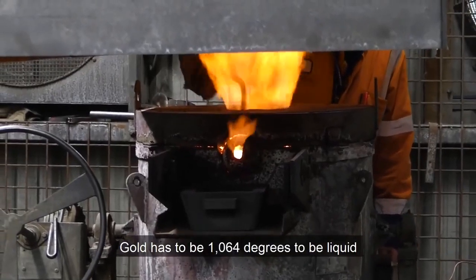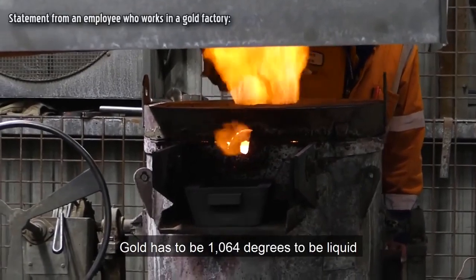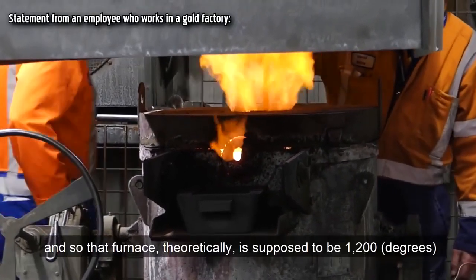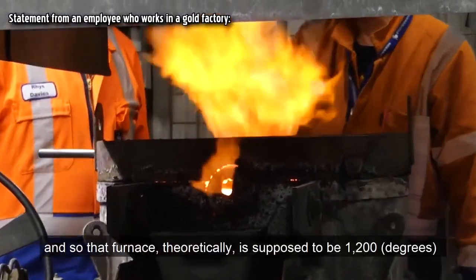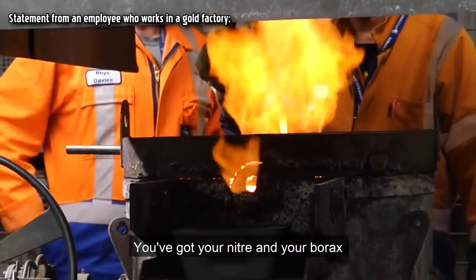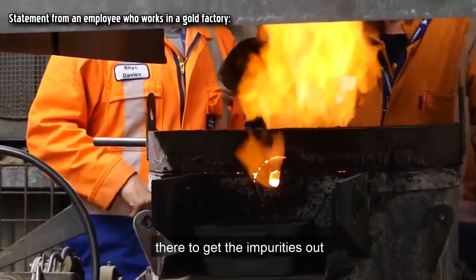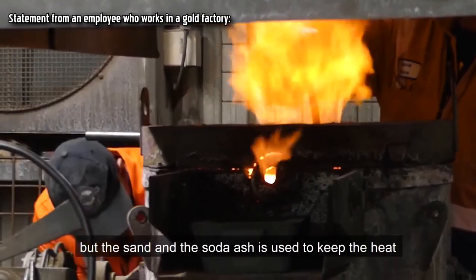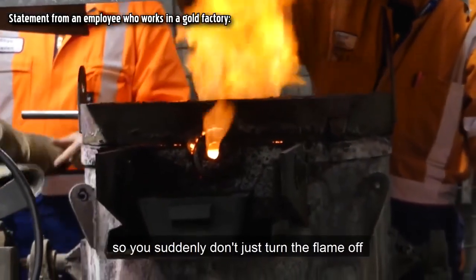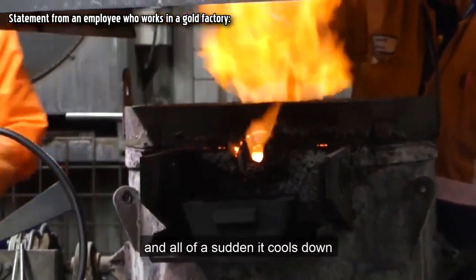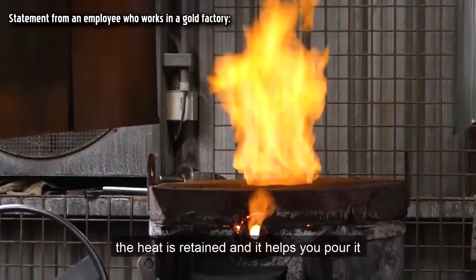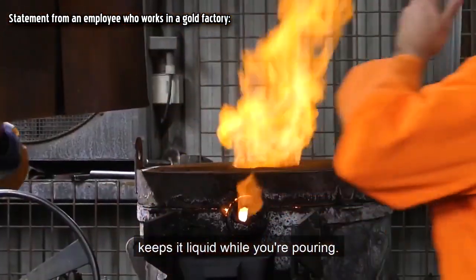Gold has to be 1064 degrees to be liquid, and so that furnace, theoretically, is supposed to be 1200 degrees. You have got your niter and your borax there to get the impurities out, but the sand and the soda ash is used to keep the heat. So you don't just turn the flame off and all of a sudden it cools down, the heat is retained and it helps you pour, it keeps it liquid while you are pouring.